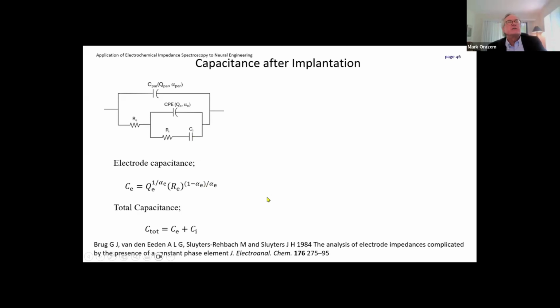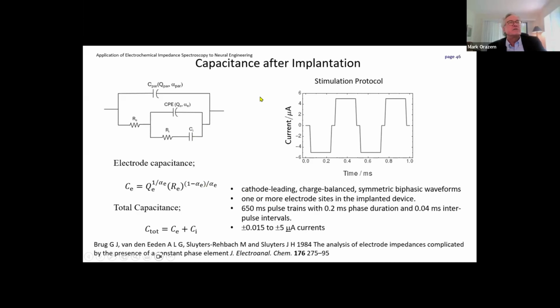reduction. Now, what's interesting about this is that these electrodes have been subject to stimulation. The protocol is cathode leading, charge balanced, symmetric biphasic waveform. One or more electrode sites in the implanted device were stimulated at the same time. There were 650 millisecond pulse trains with 0.2 millisecond phase duration and 0.04 millisecond intervals in between. I've sort of tried to draw that over here. And then the currents were basically the same for all size electrodes. They were not scaled by the area, and they ranged from 0.015 to 5 microamps.